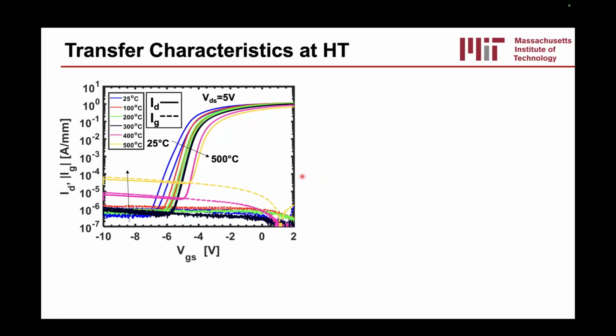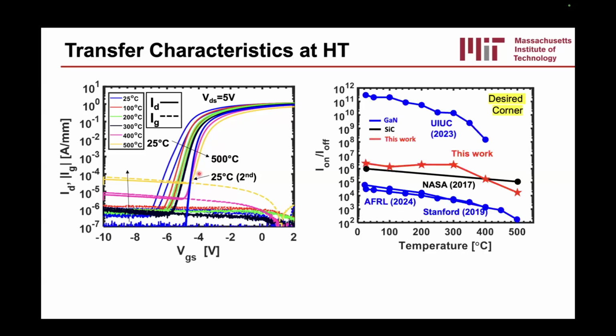Similarly, we can look at the transfer characteristics. This is a little bit convoluted here, but the solid lines are the drain current, and the dashed lines here are the gate current. And we can see as you go from 25C to 500C, there's a positive shift in the threshold voltage, and the off-state leakage, namely the gate current, increases also as we go to 500 Celsius. Similarly, if we cool down the device, we can see that there's a permanent change in threshold voltage, where now it used to be this blue here at 25C, and now after cooling, the threshold voltage has changed significantly in the positive direction.